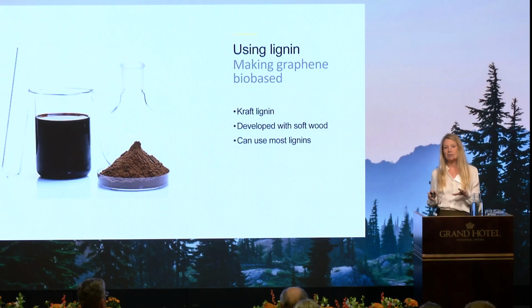But the type of wood makes more of an impact on the material. So hardwood works in general. We've tried eucalyptus, and that makes a beautiful graphene. The properties are slightly different, so it's suitable for different applications, but it's a good material. But we also tried birch, and that does not work at all. Neither does grass lignin, unfortunately. But otherwise, most can be used, and we prefer the low molecular weight lignin.